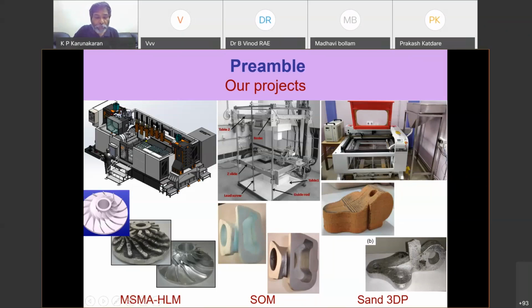So here, by going for higher number of axes, the kinematics gets complicated, and we also go for different slicing concept. Here we call it as conformal slicing. Our traditional slicing is stacking the layers in planar horizontal layers. Whereas here we are talking about putting the bead using a 5-axis motion of the gun. So it is no longer planar growth. It's very similar to the biological systems or the way a baby will grow in the womb of the mother. Okay, it grows in a conformal way, not in a horizontal layer. So that is what we were able to achieve in this.